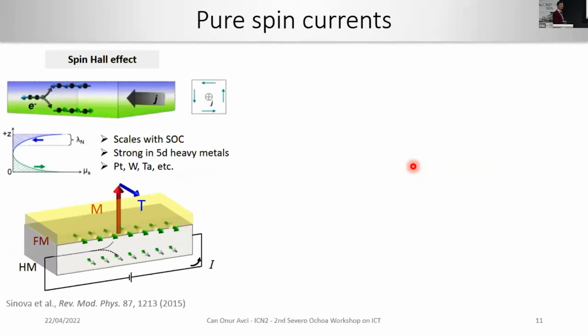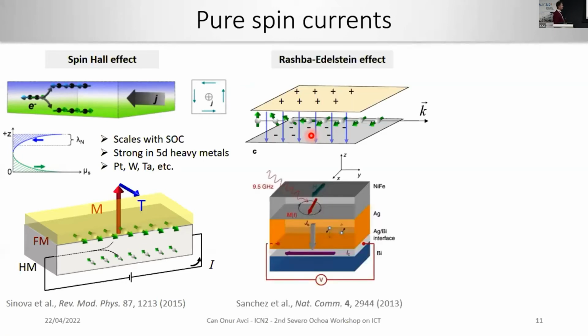So pure spin currents can actually be obtained by various physical phenomena. One of them is what's called the spin Hall effect. Spin Hall effect is an effect that is generated by spin orbit coupling in materials with large spin orbit coupling. And it turns out that when you inject a charge current into the material, this charge current will undergo spin-dependent scattering, and then spins with opposite polarity will accumulate at the opposite interfaces of the material. And this is a way to generate a spin current that travels orthogonal to the charge current. So the charge current goes in plane and the spin current will go out of plane. So this is, as I explained earlier, basically a perfect scenario to generate a pure spin current in a material that is more flexible than the spin polarized current I explained earlier.